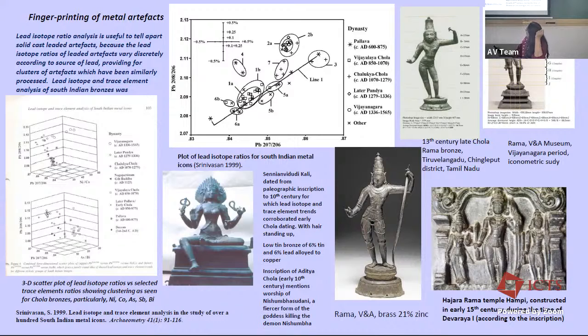But anyway, even if we couldn't pinpoint the ore sources for all the South Indian bronzes, what was quite interesting is that when you look more closely at that larger cluster, you see a lot of smaller clusters forming here. And each of these clusters has some coherence within it because they all show some stylistic and chronological consistency, which suggests that it could be smaller mines within a larger mining region which had been mined at a similar point in time and used for metal at that particular chronological point.